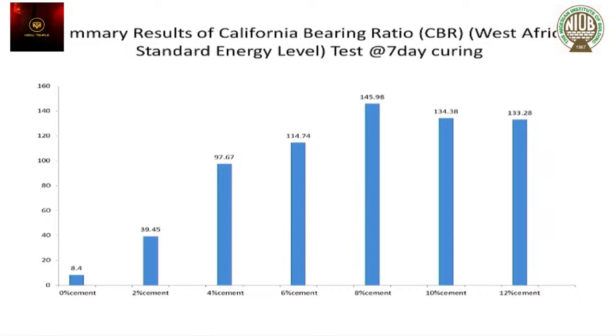The next is the summary result of California Bearing Ratio for West African standard energy level at 7-day curing. Actually, this test was subjected to 7 and 14 days. So in the course of the study, it was discovered that those materials that were subjected to 14 days curing were of better stability than the 7 days curing. And it's still on the 8% cement stabilization that we got a better result. Meaning, the 8% stabilization is recommended to be used as a pavement for road construction because it will be able to withstand whatever load that comes upon it.